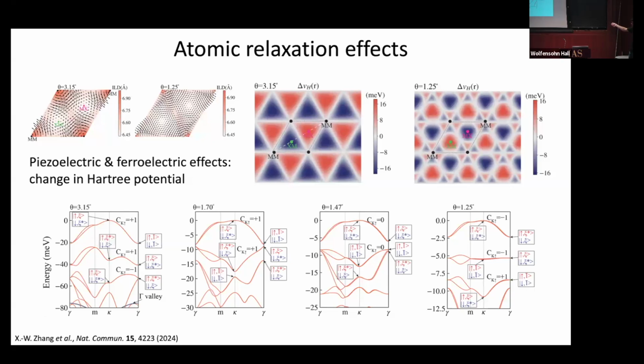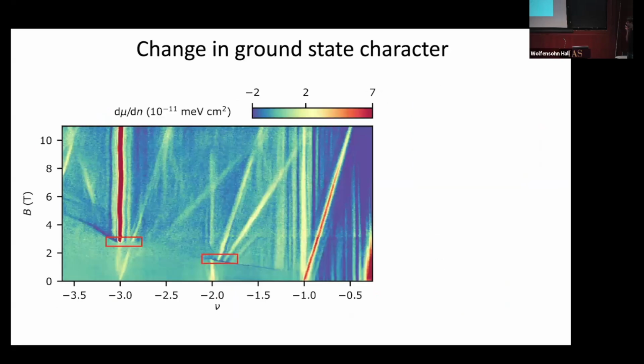The topology, actually, they predict to go away at this intermediate angle that I was showing you. So maybe that's a reason we haven't looked yet at angles 1.7 and above to see whether there's actually a change in the Chern number to opposite Chern numbers for a given value at higher twist angles. But this may be at least an explanation for what's going on in our data, to turn the topology off on the high twist angle side. Okay, so